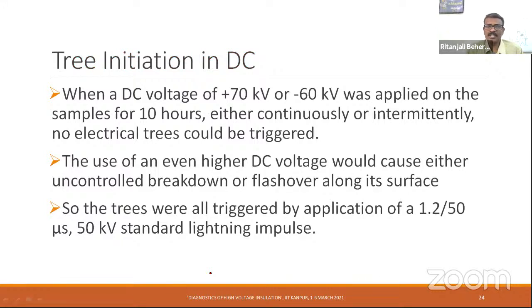So let us see how the tree initiation in DC compares to what has happened in AC. When a DC voltage of plus 70 kV or even minus 60 kV was applied on the samples for 10 hours, there was no single channel formed. Further increase in the voltage will cause either catastrophic failure, premature failure, or even flashover. So this is one reason why, in order to make the study, we cannot just initiate the tree by increasing the voltage.